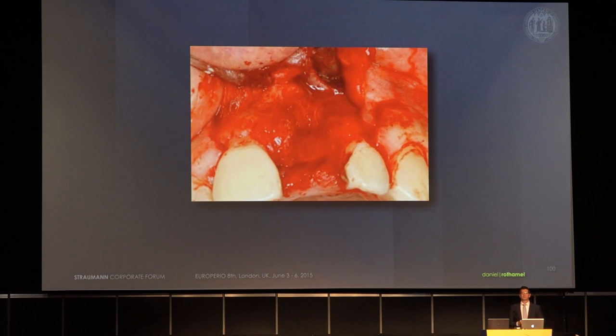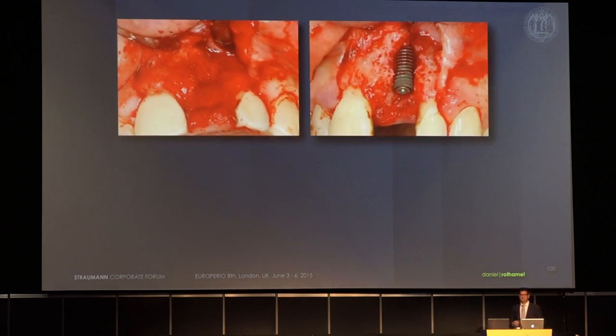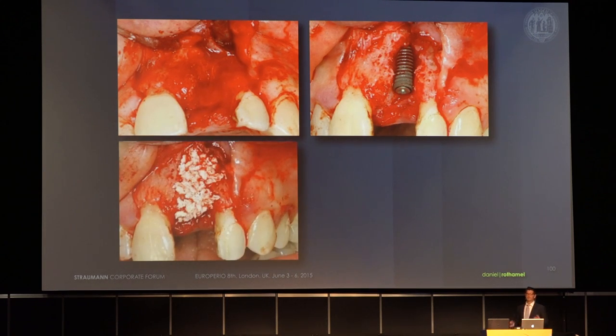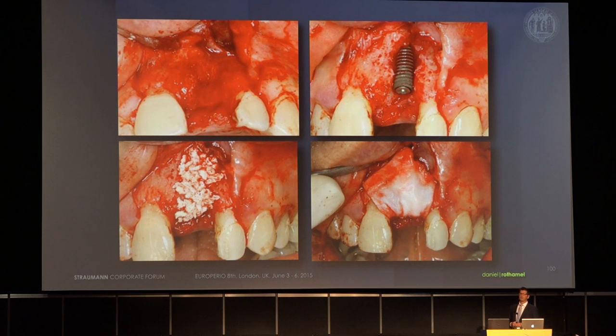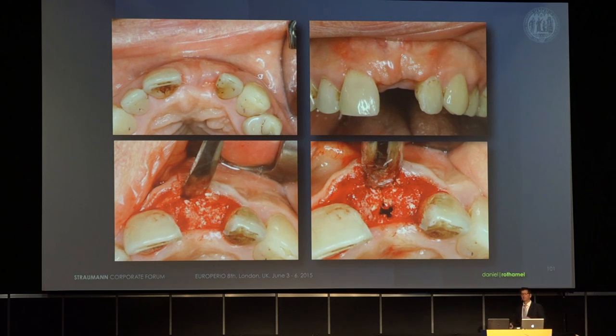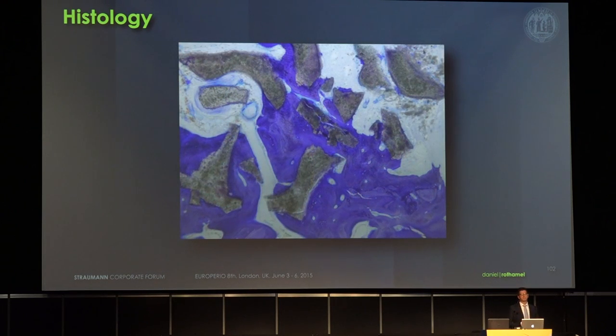The problem with quickly resorbable membranes is that sometimes the result is good but not perfect — the implant may not be completely encased in the patient's tissue. With lateral augmentation using cerabone — a sintered bovine bone substitute material — covered with a BioGide membrane, at reentry we see nice bone formation, but some particles remain soft tissue encapsulated. Histologically, we see areas where bone substitute material is embedded in newly formed bone matrix, but on the surface some areas are just soft tissue encapsulated.